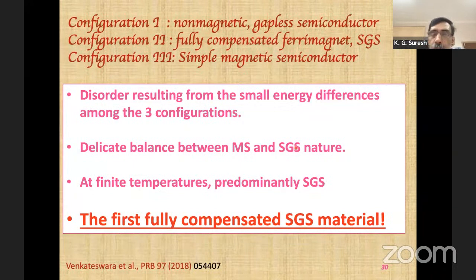This is very difficult to say from the experiments, but when you do a calculation, theory, and compare with all the details, a lot of work is needed. We could conclude that this is actually a completely compensated spin gapless system at room temperature. At room temperature, the spin gapless nature wins because the energy separations are such that, among the three crystal configurations of the structure, that is what we showed some time back.